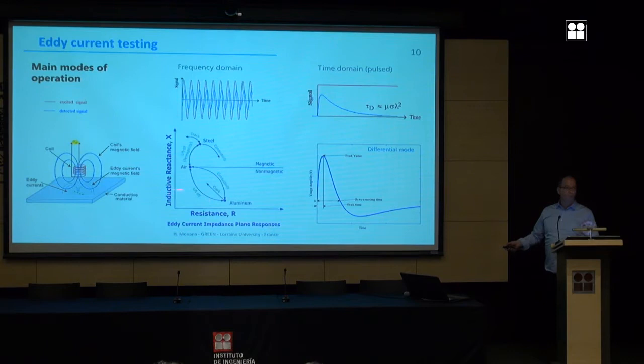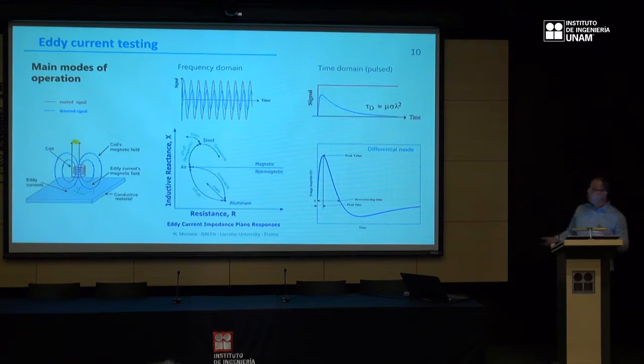If we put the coil above the aluminum, the presence of a crack will give a response in this direction, and the variation of the conductivity of the tested material will be in this direction, in this way. These are typical responses. We can also work in the time domain.